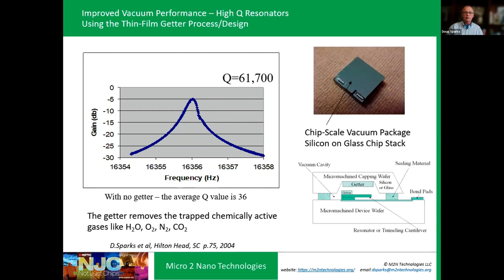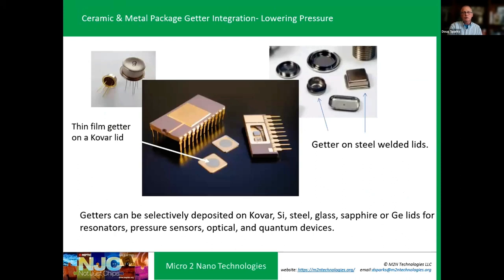So it's actually absorbing these materials, and these gases come off the surfaces, even though your bonder might be bonding at a pressure of less than a millitorr. Without a getter, the desorption of these gases from the surfaces will result in a pressure of around 1 or 2 torr. So think of degassing and using integrated getters to improve that. And this can also be used on ceramic and metal packages. Again, this is more commonly used in aerospace applications or infrared sensor applications. And they've selectively been deposited on germanium lids and windows, sapphire, Kovar, stainless, et cetera.